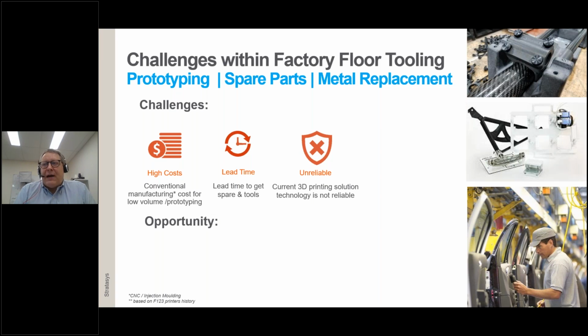Obviously, metal produced part. We have done several comparisons, and we see very often that if you machine a prototype out of an epoxy block material or out of aluminum, for example, both, we achieve sometimes up to 98% cost reduction by just printing the part you need. We have a nice example I'll show you later on. This can be printed during the coffee break. It's 30 minutes and then the part is available. Try this on a milling machine.